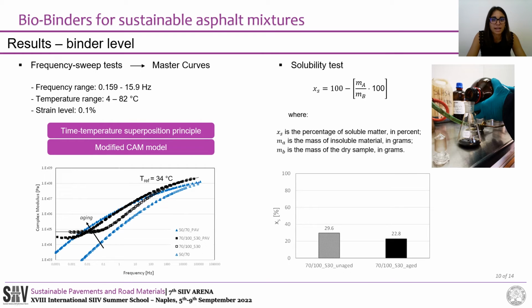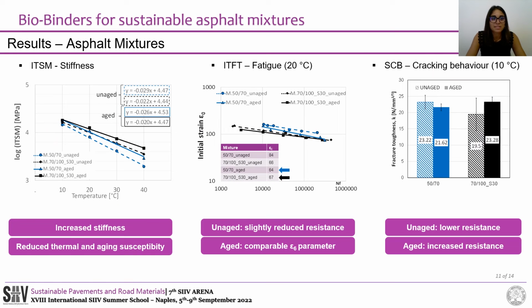At the same time, solubility test highlights a reduction in the soluble matter after aging, which could mean that part of lignin generates chemical bond with bitumen becoming part of it. Passing to the asphalt mixtures, from the ITSM test, the lignin-based one confirms the higher stiffness experienced at binder level at all the investigated temperatures. At the same time, the lower thermal and aging susceptibility is also confirmed.